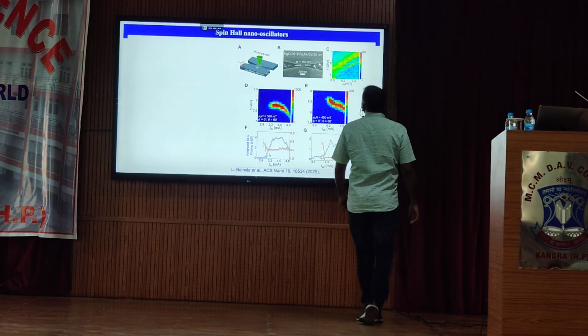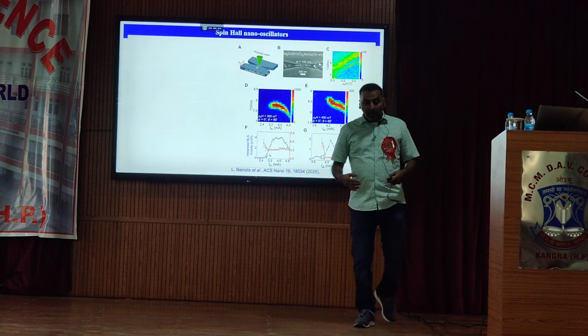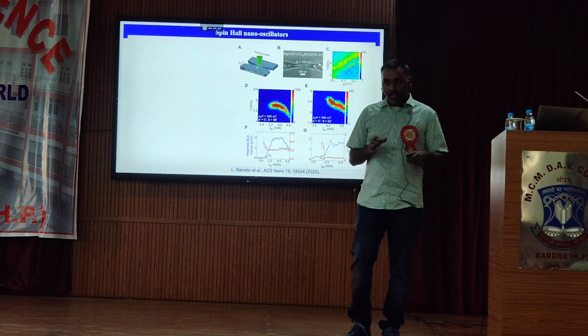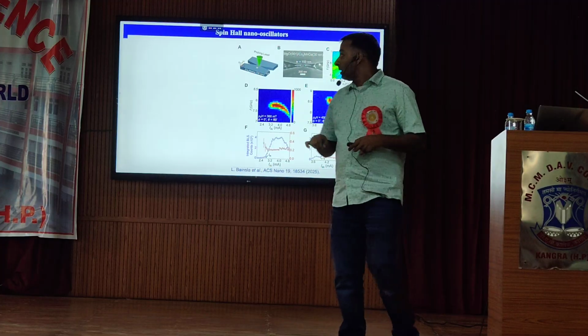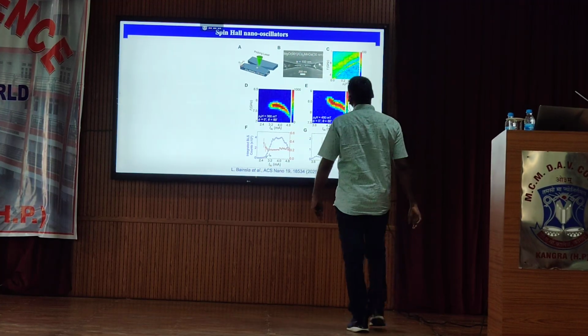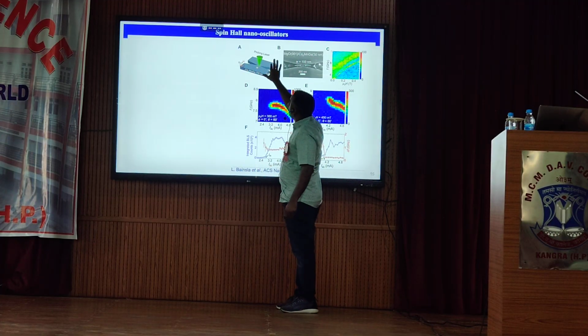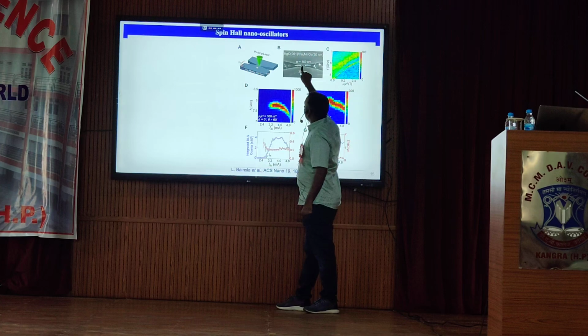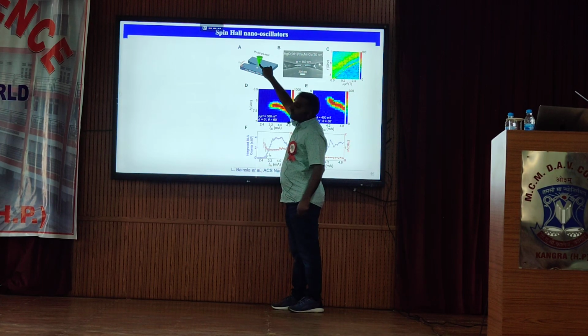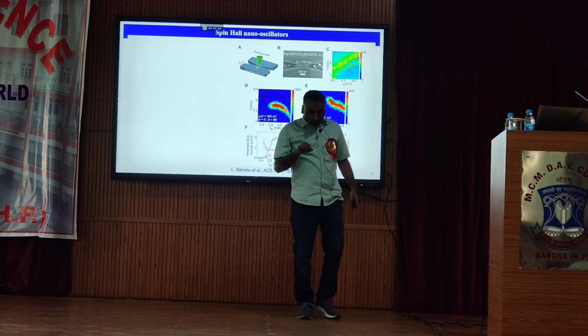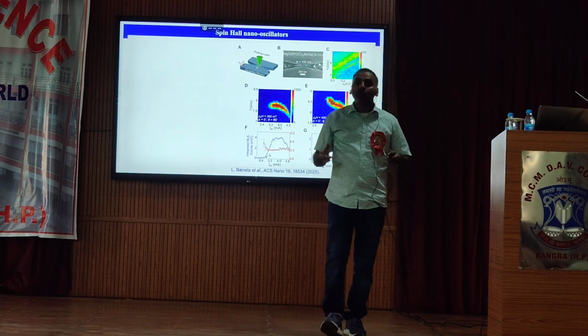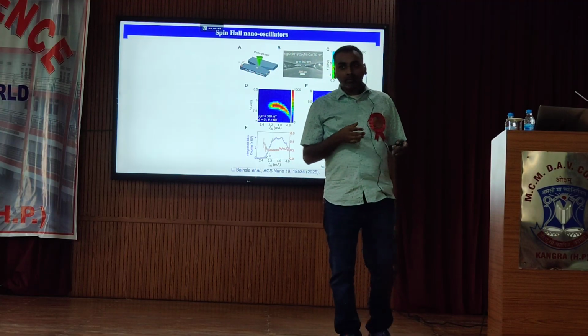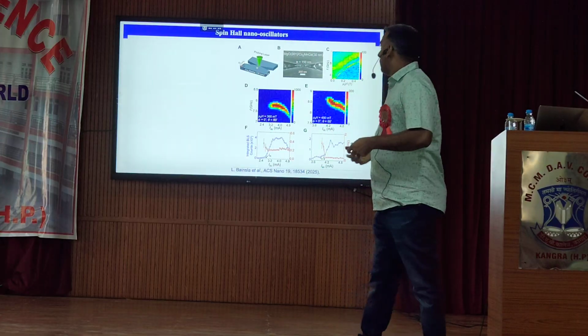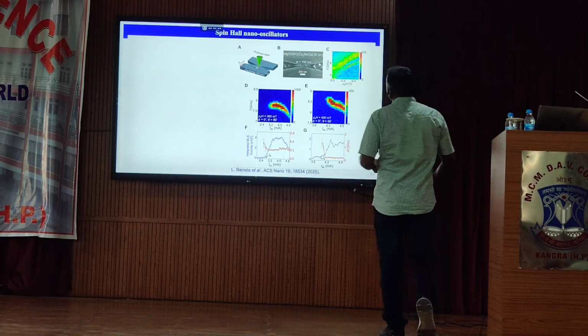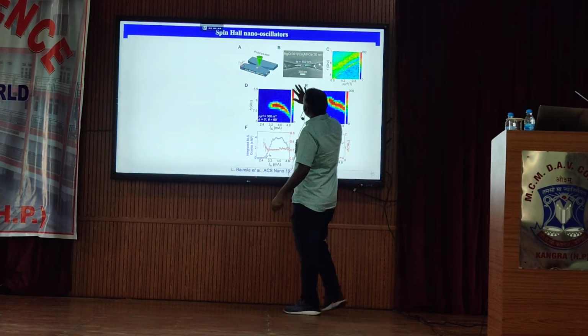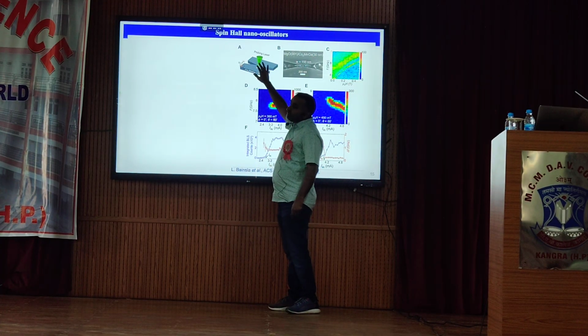We use micro-focus Brillouin light spectroscopy, which is a direct optical technique which applies a laser pulse to our sample surface. As you can see in this schematic, we have our devices here. So on the nano-constriction region, we apply a probing laser. When the laser pulse falls on the material, it can interact with the material in different ways. It can interact with the phonons of the material or the magnons of the material. Depending on the reaction of this laser with the material, we can say what the outcome will be. Since this is a magnetic material, we can expect that the laser will interact with magnons.